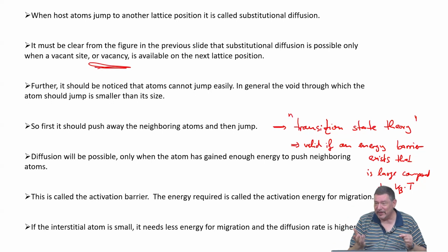So it's the Arrhenius representation, which goes back to rare event statistics and transition state theory for processes which are limited by activation barriers that are large in comparison to kBT. All the processes I know that follow this statistics can be described by the Arrhenius law in terms of activation, right?